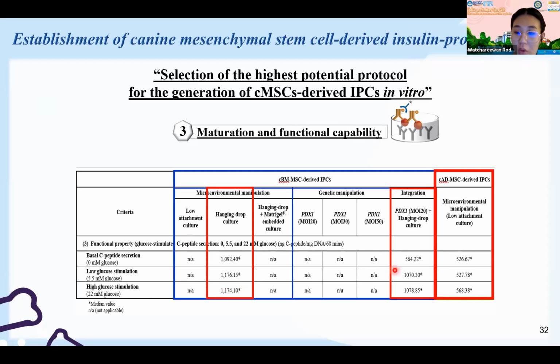While the integration method of the bone marrow and the microenvironmental of the adipose mesenchymal stem cell, even though they start from a low concentration of C-peptide secretion, when we challenge with the glucose concentration, they can upregulate a little bit, like a dose dependent secretion. However, we still do not see a significance between each group.